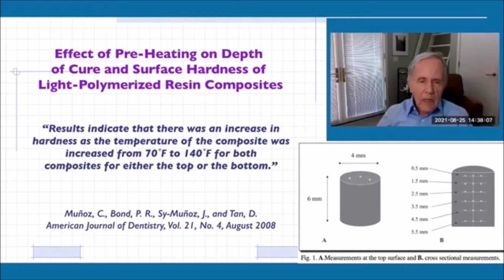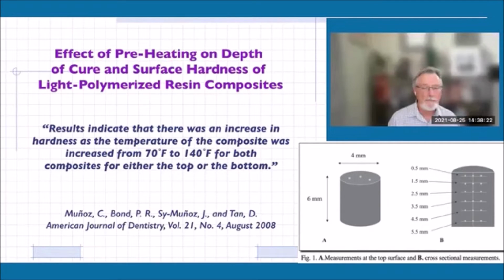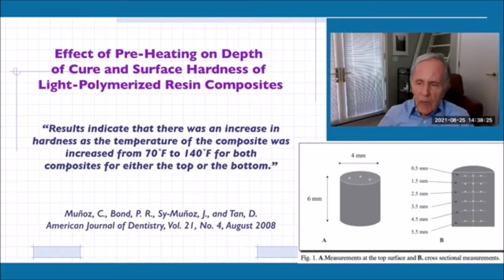What they found was that they had much higher bottom hardness when it was cured with the heated composite. And they did that both with an LED light and they did it with a halogen light. So again, from another point of view, if you're looking at hardness, that certainly correlates with the monomer conversion or the curing. And it's nice to know that your material is fully hardened. It's pretty obvious that a harder material is going to be stronger. It's not going to fracture as easily. It's not going to allow materials to leach because it's not going to wear as much. So all those things together gives us better performance and, of course, reduced sensitivity for the patient. Awesome. Thank you, Josh.